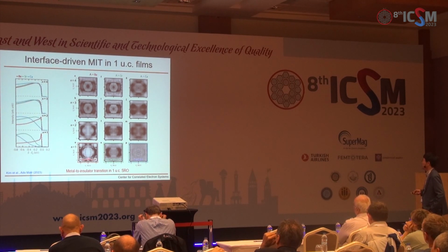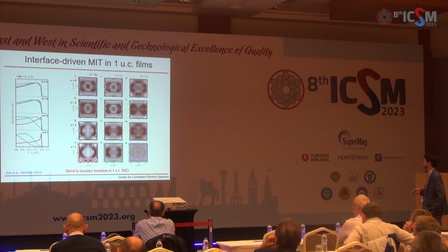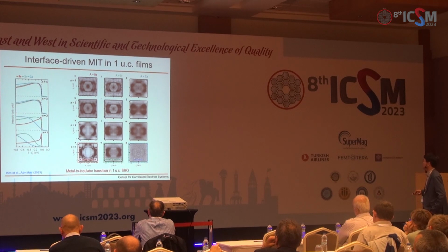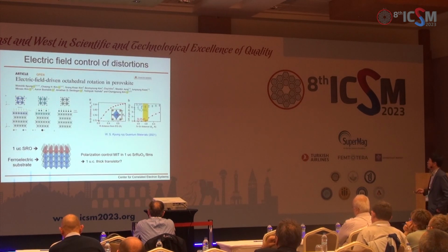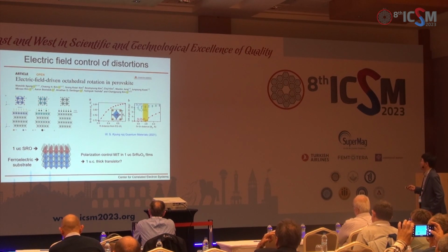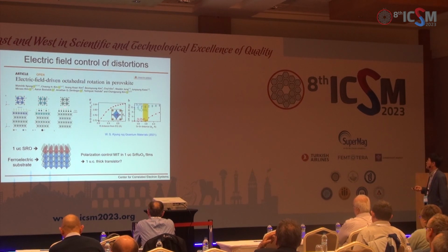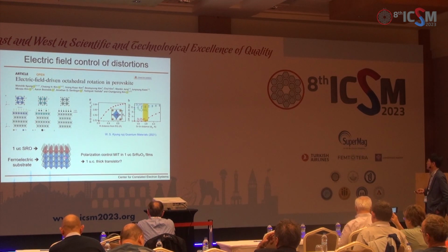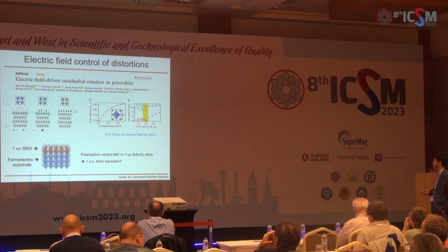Okay. So we have a coherent metal here in one unit cell strontium ruthenate on PTO and an insulator. So we could change all the way from insulator to correlated coherent metal of one unit cell strontium ruthenate. What this tells us is that by controlling this octahedron distortion, we can change from insulator to metal. So one can possibly imagine growing SRO on a ferroelectric substrate, and maybe you can change the property from insulating to metal using this ferroelectric substrate. There's some suggestion from our work that that's possible by changing polarization of this ferroelectric substrate.